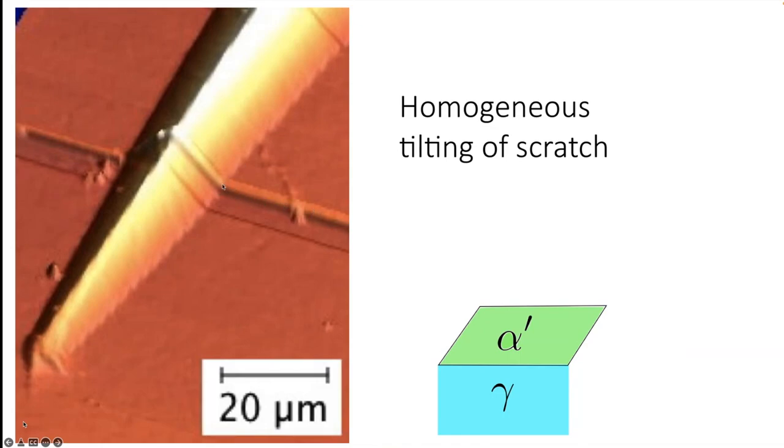In other words, there is absolutely no displacement within the plane between the martensite and austenite. So on this schematic diagram, the scratch is continuous across this interface, showing us that there is actual complete coherency at the interface between austenite and martensite. Of course, you need more than one scratch to determine that there is no distortion in the habit plane. I've only illustrated one scratch here, but you could have scratches going in different orientations, and all of them would maintain continuity at the interface.